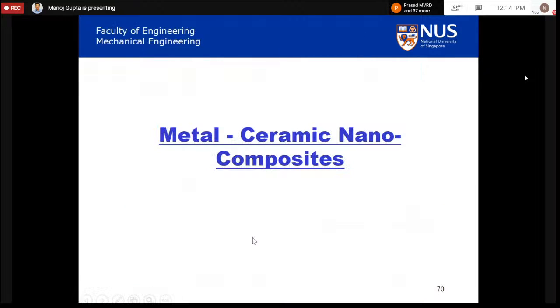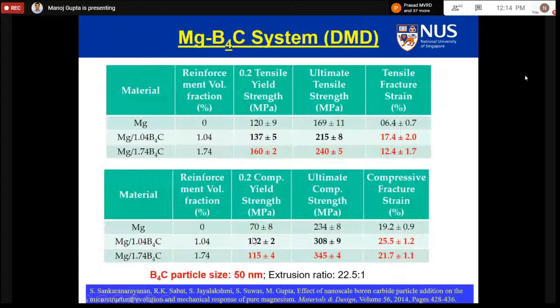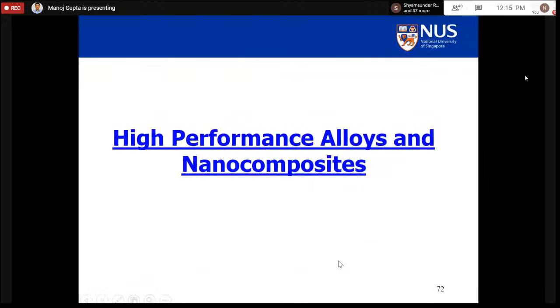You can also put ceramic particles like boron carbide, and you see here again your ductility is doubled from 6% to 12%. Anything more than 10% is wonderful for a manufacturing engineer. You can give your material a shape that you want to give. Any intricate shape you can give. Compressive properties also increase. So nanoparticles are the ones which can give you a simultaneous improvement in the strength and ductility.